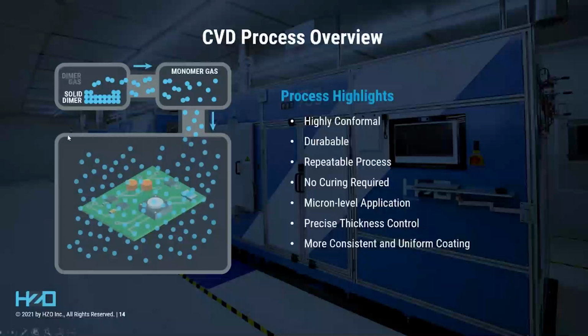On the right, we have most of the process highlights. These are items that I've mentioned previously about Parylene. As I said, highly conformal. Because it's a vacuum process, it's very repeatable. It's a microns level application, so those molecules can integrate into even very small spaces, and you have very precise thickness control throughout the chamber.